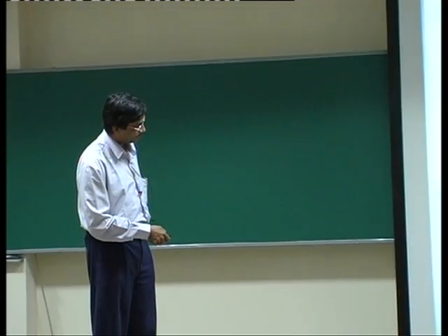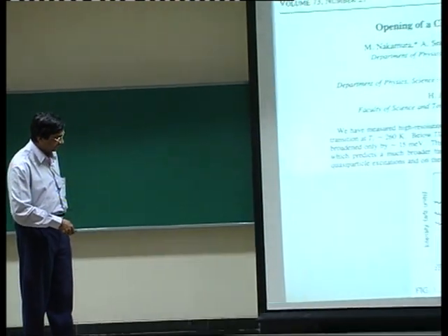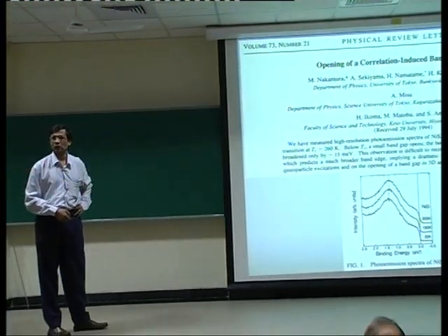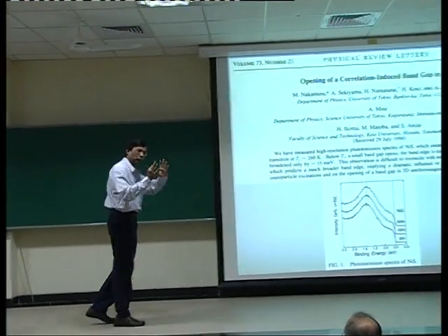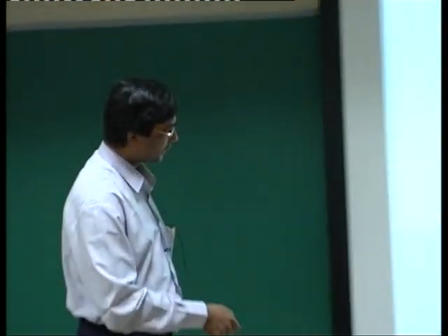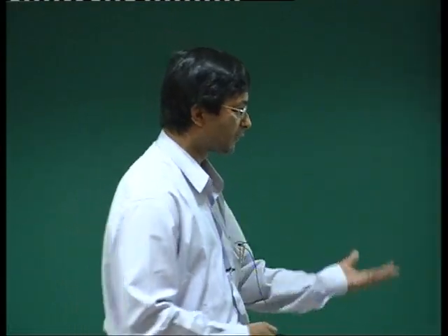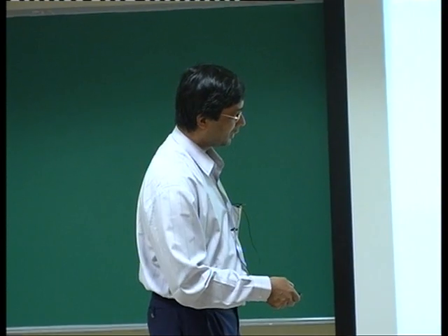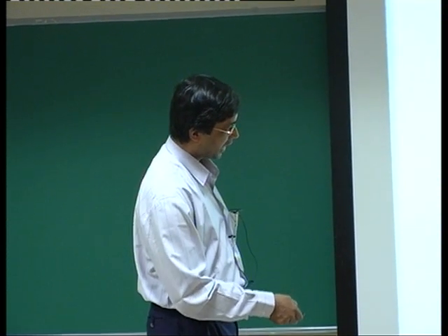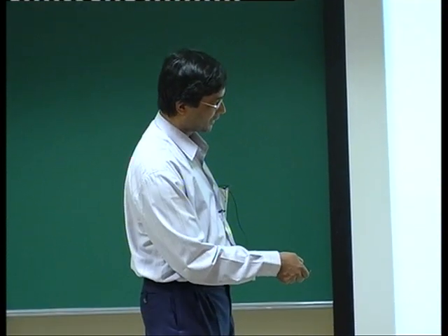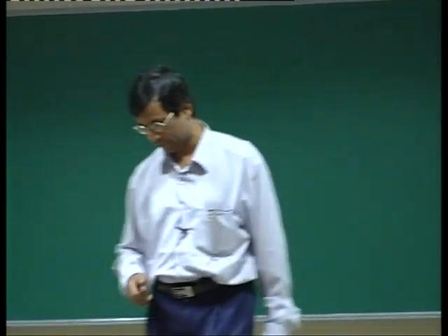But before that, the observation that was made is that, look, as we lower the temperature, this main peak position shifts to the left. Left implies higher binding energy. So the nickel states are getting pulled down, and if it is shifting down, it can effectively open up a gap here. So it is indicative, suggesting that there is a gap here, by looking at the high intensity peak somewhat down in energy, and there's a little bit of shift there.